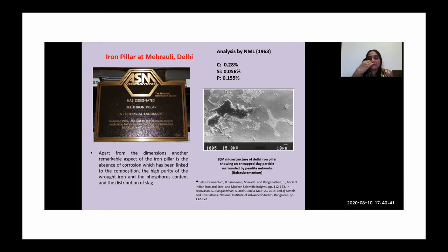And so we were also involved in the nomination, some of the colleagues at NIAS, like Dr. Valde Raj and Professor Ranganathan and so on. And the plaque says, of course, a rustless metallurgical marvel dedicated to ancient iron making traditions and blacksmiths. And of course, apart from the dimensions, one of the remarkable aspects of the Iron Pillar is the absence of corrosion, which has been linked to the composition and the high purity of the wrought iron, and the phosphorus content and the distribution of slag and such like.